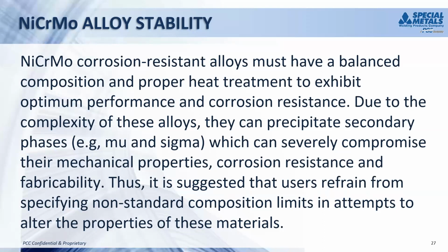So my suggestion would be, if you're using these materials, stick with the ASTM specification for the chemical composition. We've seen cases where customers have asked for increased molybdenum content or different variations on our standard composition with the idea that they can improve the corrosion resistance. But the fact is, if, for example, with C276 or 22 or 686, the molybdenum gets too high, then you start precipitating mu phase, which actually decreases the corrosion resistance. So leave the chemical composition to the existing specs and the experience of the metal manufacturers. The next slide.